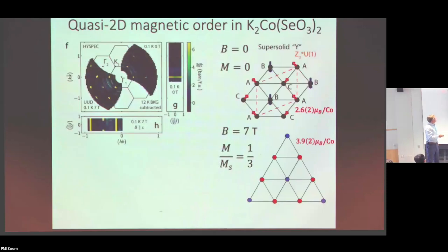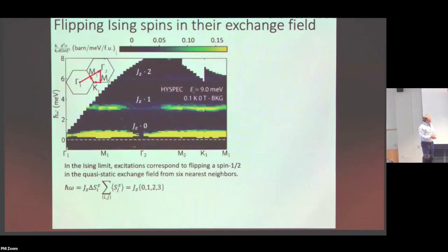All right, so because the moment is heavily reduced relative to the full saturation, it means that there must be some quantum fluctuations. And so we're going to look for those using the inelastic scattering technique. That's a natural way to do that. And this is what it looks like. So this is 0 field and very low temperatures. And the machine is counting the neutrons as they come off. And this is my wave vector axis, the various indexes for wave vector transfer in the Brillouin zone of the triangular lattice.